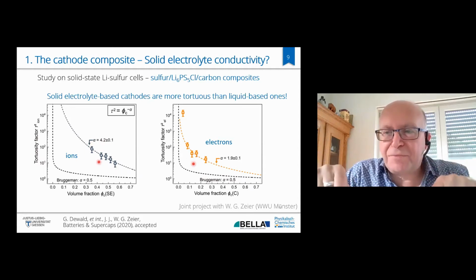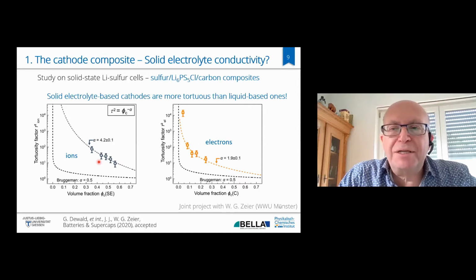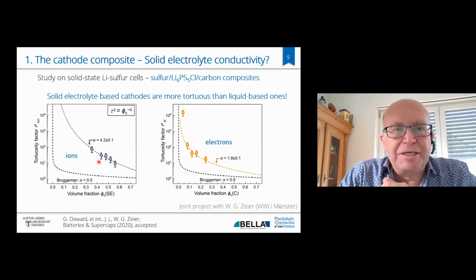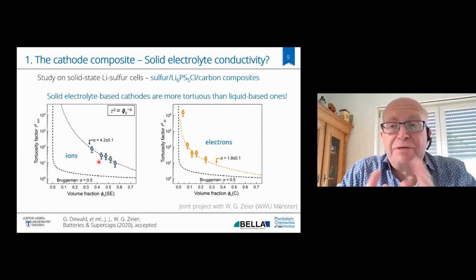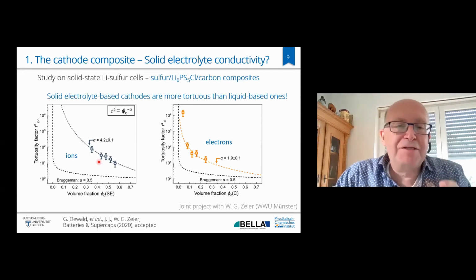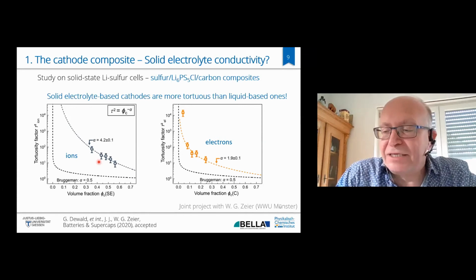So the microstructure of the cathode composite with a solid electrolyte is far more critical, I would say, than with a liquid electrolyte, because the liquid electrolyte impregnates the porous structure, has no grain boundaries, no dislocations, is always more or less the same. But if you deal with a solid electrolyte, it really adds complexity to the microstructure of the cathode composite, and that has to be taken into account. So that is the reason why only the best solid electrolytes with ultra high conductivities can be used in cathode composites. Now, that means, of course, that other electrolytes, phosphates, oxides, can be used as separator electrolytes, where if you have a thin separator electrolyte, the conductivity does not need to be that high.